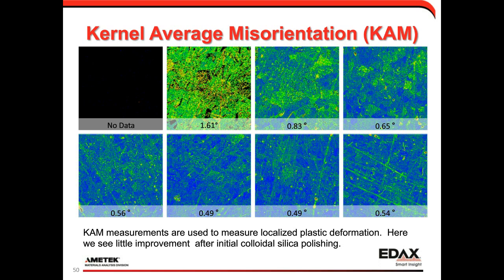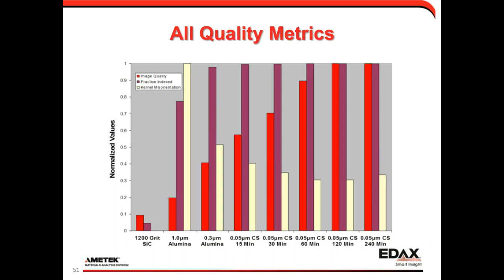And so if we show all three of these metrics on the same chart, you can see generally if you aim for about 1 hour of colloidal silica, you'll generally be in the neighborhood. Obviously, this is for a nickel superalloy. It's a relatively easy sample to do for EBSD. But the same methodology can be used on all sorts of materials if you really want to optimize things. It gives you an idea of what you would look for in different materials: image quality, indexing rate, and misorientation, to get an idea of whether your preparation is good enough for what you're trying to measure. And generally, if you're worried about deformation measurements, you might have to do a little bit more polishing than you would if you're just interested in texture type measurements.